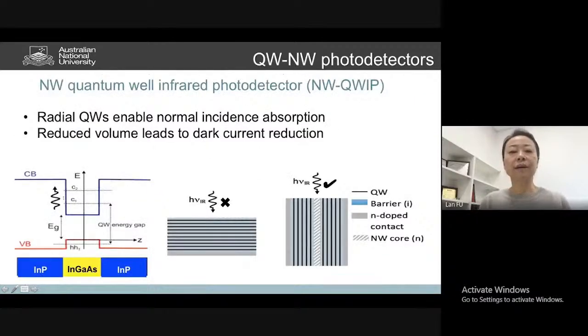And finally, I just want to touch on this: I mentioned that once you have quantum wells inside nanowires, you can also employ inter-subband transitions within the conduction band. The advantage is that the energy levels between inter-subbands are much smaller compared to band-to-band transitions, so you can use them for mid-infrared to long-infrared photodetection, which is very useful. However, from quantum mechanics, we know that this inter-subband transition will not happen for normally incident light. So if you grow planar quantum wells, normally incident light cannot be absorbed. So in this kind of detector, QWIP, as we call it, using the inter-subband transition, we have to create a grating structure on the surface to enhance light scattering and then achieve this photodetection.